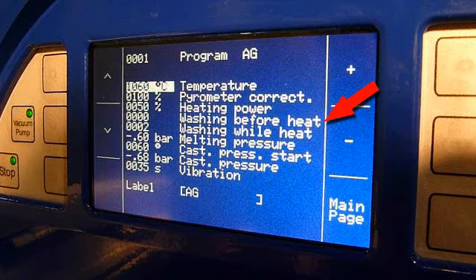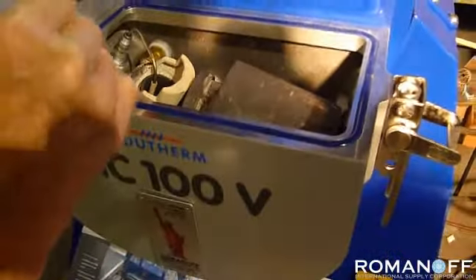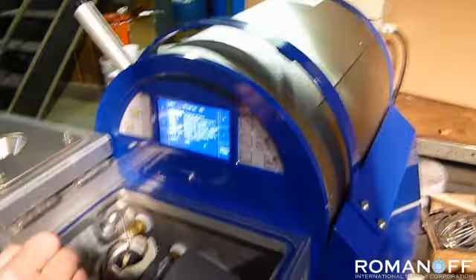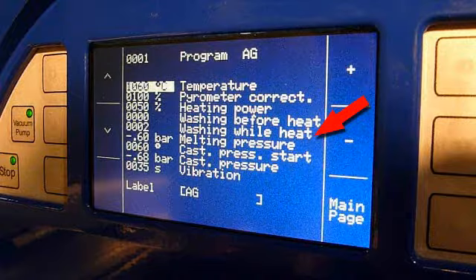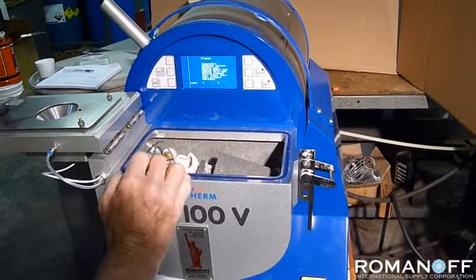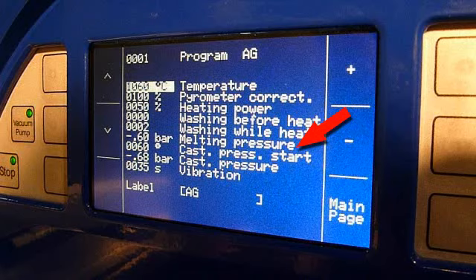A wash cycle is a combination of vacuuming and an introduction of argon gas to clean out the chamber of any gases that may be in there. The next parameter is the washing cycle while you are heating, and you can determine how many washing cycles you want to use. The next one is the melting pressure. That means the amount of vacuum that the chamber will be under during the melting.